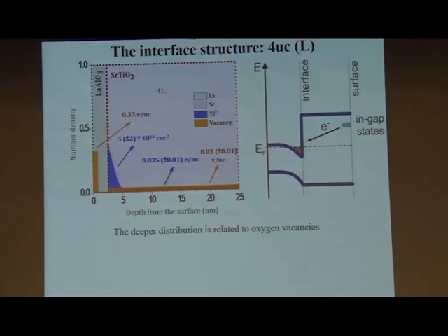And therefore, you are weakening the oxygen bond, and it prefers to go away. So the vacancy gets created, and electron gets transferred sequentially. But arising from this polar catastrophe or the polar field that grows up, bending, and therefore stabilizing it, you have in-gap vacancy states which contribute to the electron, and those electrons provide you this interface exactly in the order of magnitude that you would expect.